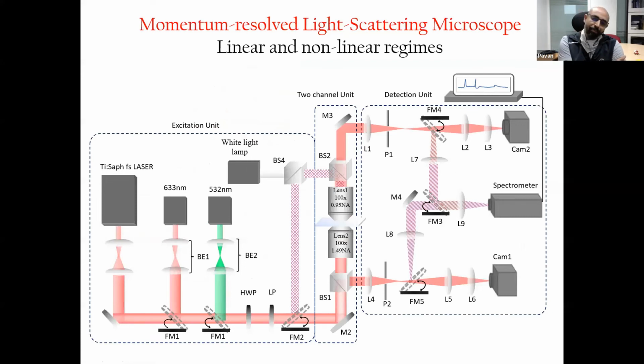Now, this we have really built like a Gaudi's building, in the sense we have piled up a lot of different methodologies, including nonlinear optical techniques, where we can look into momentum-resolved light scattering in the optical trapping regime down to single nanoparticle scales. And this is a very versatile method because it creates a unique opportunity to look at, let's say, second harmonic generation, two photon luminescence, nanoparticle assemblies and nanoparticle traps, which you can create in such a situation. And we are now also pushing the limits towards single particle trapping and optothermal assembly on various different geometries and other structures.